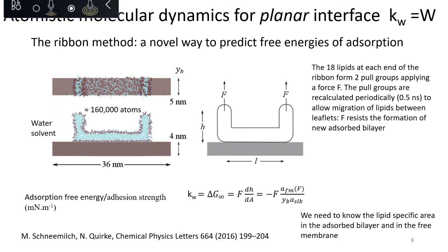We have restraining forces on the two ends that stick out into the solvent, which is water, and we measure the free energy of adsorption of that leaflet of membrane bilayer by essentially measuring the force required to keep it stable on the surface.